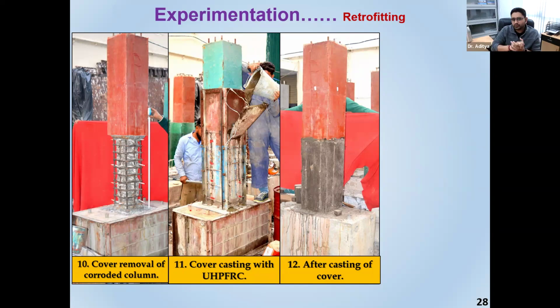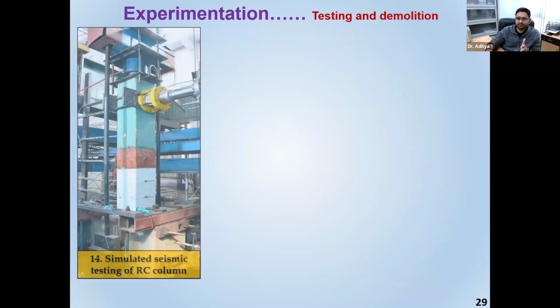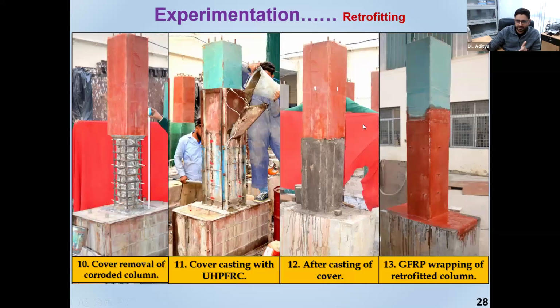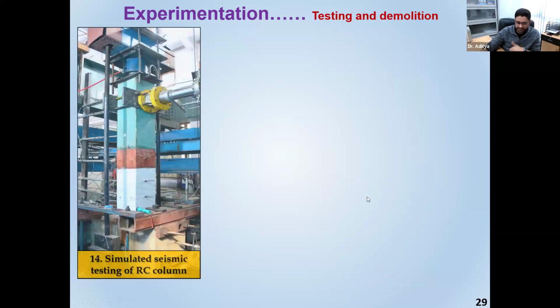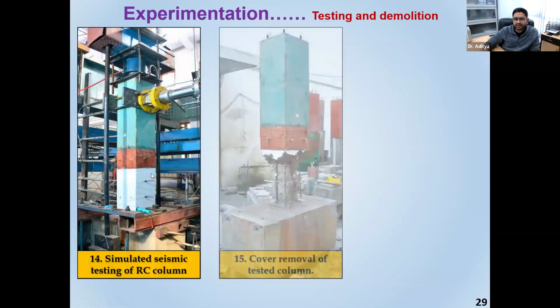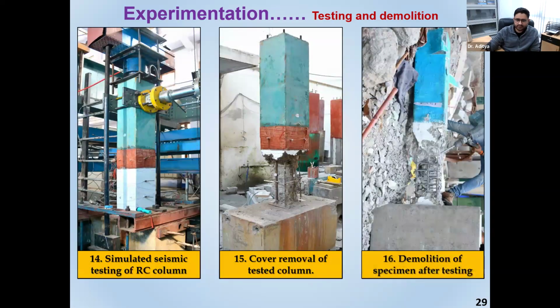If the performance is found to be not good enough, we will again cast a column, corrode it to 10%, remove the cover concrete, retrofit with UHPFRC, and now retrofit with one more layer of GFRP. That's how the experimental plan has to be. You can see the retrofitting with the GFRP as well has been done, and then they were tested. Once they were tested, they were demolished. Their rebars in this region were removed in order to visually inspect how the corrosion has occurred, and what the pattern of corrosion is.